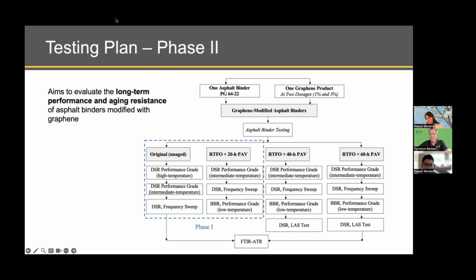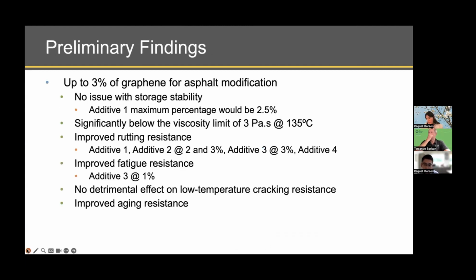I guess the only thing I would add at this point is to tie back to the concluding slide that you showed earlier, saying that based on these preliminary results, we saw the improvement in rutting resistance and also improvement in the aging resistance. This is something that we have discussed with Terrence before. Right now, at least in the United States, the primary distress in asphalt pavements is cracking, okay? And if we go back in history about 25 years ago, our industry was struggling with rutting, which is the deformation distress. But now we don't have rutting issues, okay? We are having cracking issues, which have a lot to do with the quality of the asphalt binder, and aging plays a significant role.